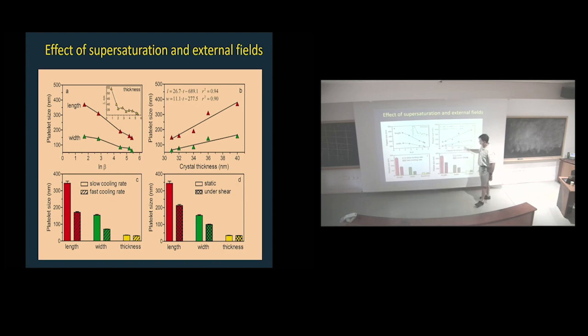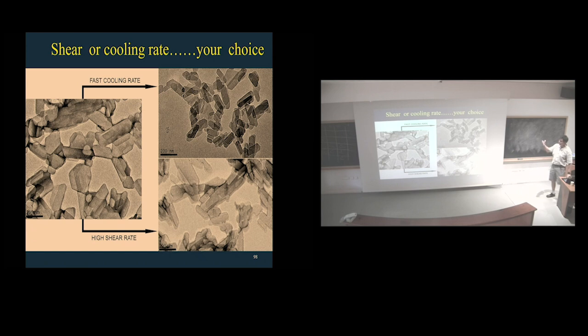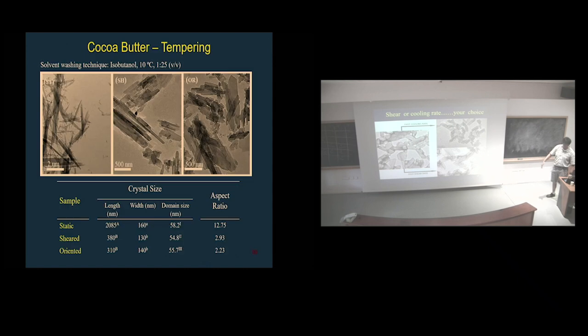Forget the thickness. If you actually do slow cooling, fast cooling, look at those huge changes in the length and the width. You don't affect the thickness too much. I'm still trying to do that. And shear, you shear it, you can change size dramatically at the nanoscale. So maybe you have a structural target for your functionality, you have a nanoscale picture. You can do it with cooling rate, or you can do it with shear rate.